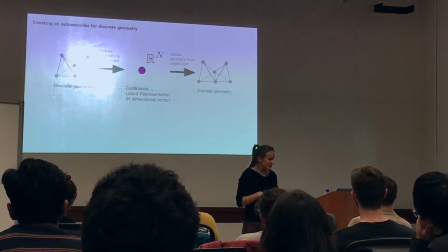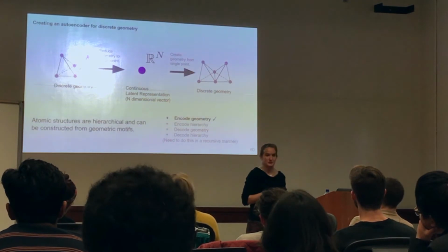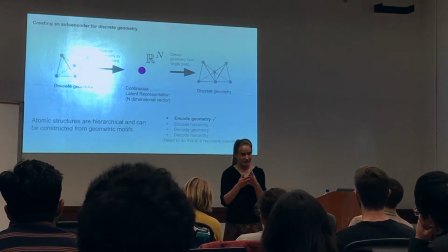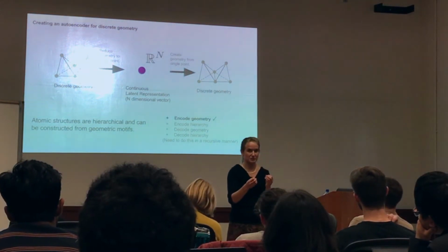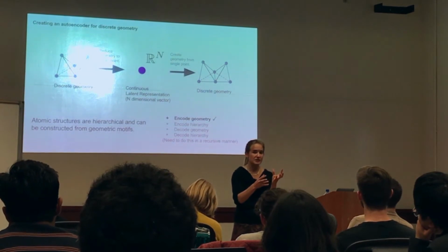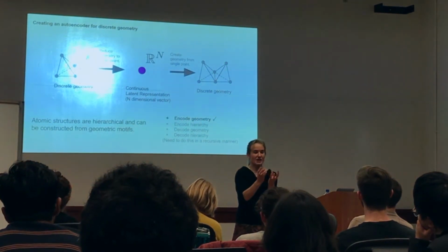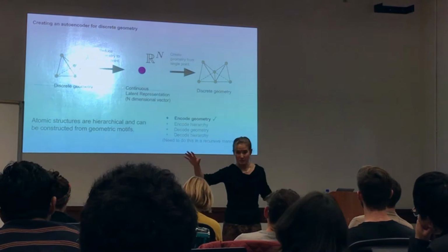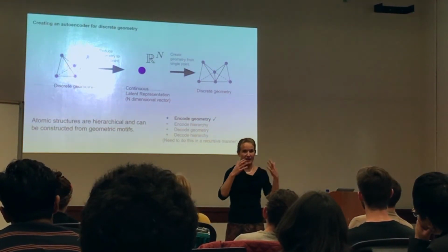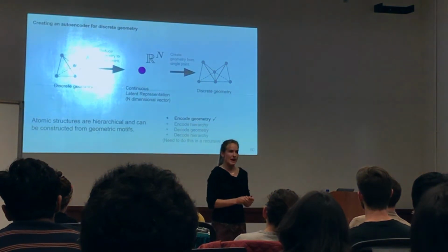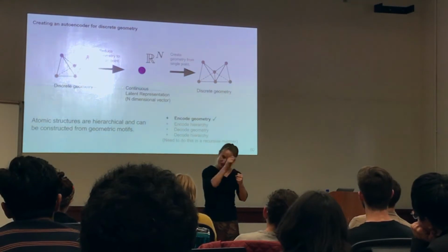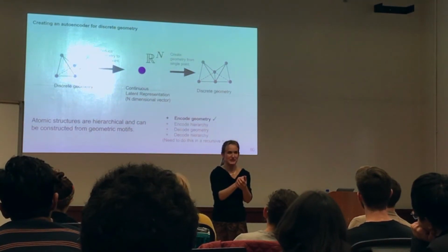In order to do this, I think we're going to have to look closely at the structures that we're interested in and notice that atomic structures have a lot of geometric motifs that they're built of. You'll have an atom, it's coordinated by other atoms, maybe in the pattern of an octahedron. Those octahedra might share edges, and then those edge-sharing octahedra might make a honeycomb network. All the atomic structures we're interested in have these geometric patterns. So how do we encode local geometry, collapse points down, and then do the same thing and continue to collapse points down until we get points?